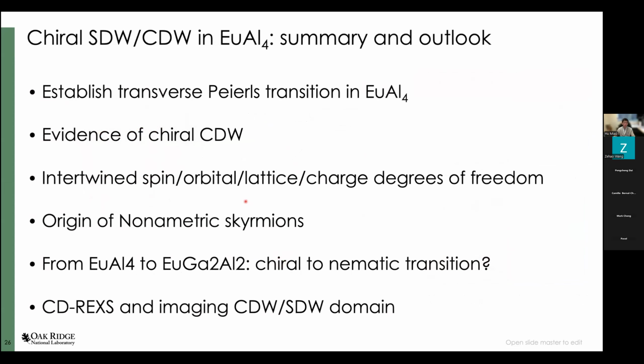So basically, I think we have strong experimental evidence to establish the transverse Peierls transition in europium aluminum 4. We have quite strong evidence supporting a chiral lattice distortion in the CDW phase. And we're quite sure in this system, the spin, orbital, lattice, and charge degrees of freedom are strongly intertwined. And looking to the future, we believe this knowledge may help us understand the origin of nanometric skyrmions.